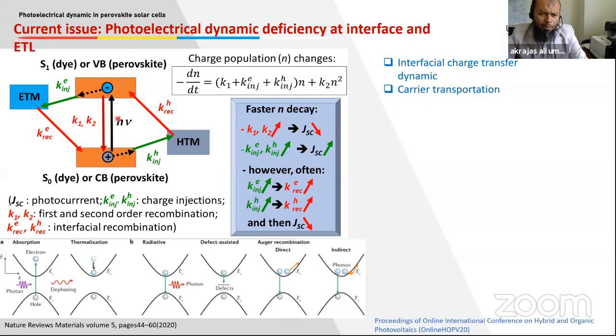So some of the excited carriers can be recombined back via band-to-band transition or radiative transition, or via defect-assisted recombination. So we will lose precious hot carriers in this case, so we may decrease photocurrent. Okay, now let's say the exciton successfully reaches the interface, then it may dissociate into hole and electron,